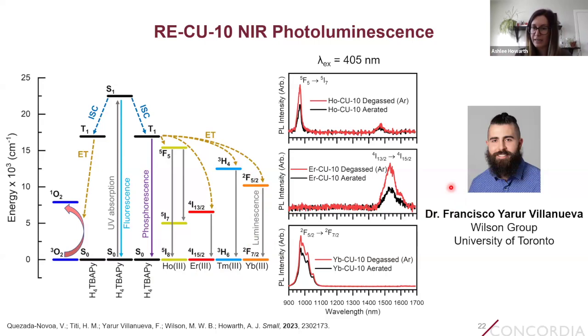And so we did this work in collaboration with Dr. Francisco Yarur Villanueva, who at the time was a PhD student in Mark Wilson's group at the University of Toronto. And Francisco collected these near-IR photoluminescence spectra for us, where we see for holmium, erbium, and ytterbium, this near-IR metal-based emission, confirming that that linker to metal energy transfer takes place.